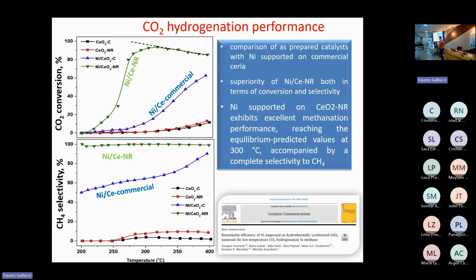And here we can see the output of this fine-tuning strategy: the CO2 conversion and methane selectivity of the optimized nickel ceria nanorods catalyst in direct comparison with a nickel supported on amorphous commercial ceria sample. The superiority of nickel ceria nanorods, both in terms of activity and selectivity, is obvious. It exhibits an excellent methanation performance, achieving the equilibrium predicted values at very low temperatures, at about 300 degrees Celsius, accompanied at the same time by complete selectivity to methane.